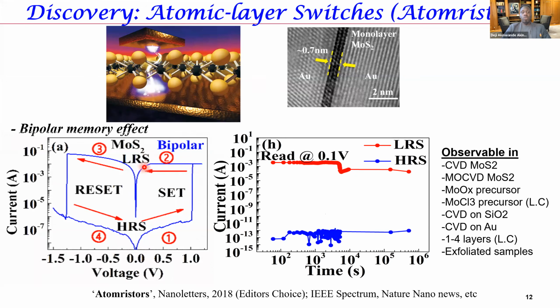So this is non-volatile, which means if you turn off the power, it's going to stay in the last state that it was. If it was in the high resistance state, the blue curve here, if you turn off the power and keep measuring the resistance or current for weeks and weeks - this is a week-long measurement - it's going to stay in that state. If it was in the high current state, the red data here, again it will stay in that state. So it remembers the last state and stays there until it's reset.